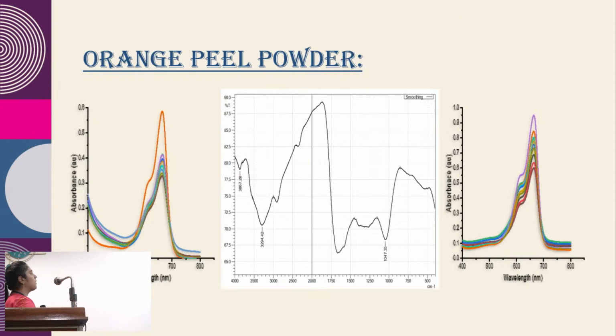For the orange peel powder, the first graph is for the raw treated sample and the other is for the one treated in nitrogen atmosphere. Of the two adsorbents, the raw treated peel has the highest adsorption efficiency. In orange peel, the first FTIR peak corresponds to the COH, the next corresponds to the OH groups, and the last one may correspond to the presence of primary alcoholic groups.